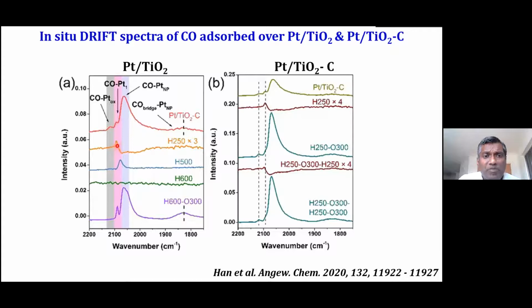Now, when you reduce the catalyst at 250 degrees C, you can see a substantial reduction in the peak area of CO adsorbed on the platinum surface. Or in other words, the platinum is not available for adsorption. When you heat it at 500, you can still see a very substantial reduction in the CO adsorbed on the platinum surface. The same catalyst reduced at 600, absolutely no platinum exposed. Or in other words, the platinum is completely covered by a titania overlayer. But when you take this catalyst and oxidize it at 300 degrees C, you get the peak back. Or in other words, the platinum site is exposed. So this process is a typical characteristic feature of SMSI, strong metal support interaction.